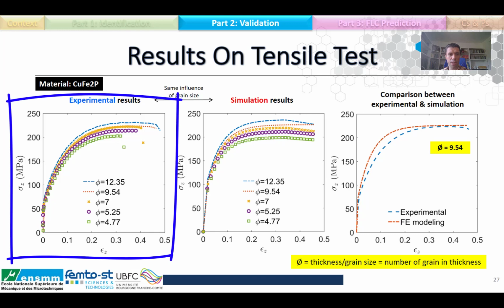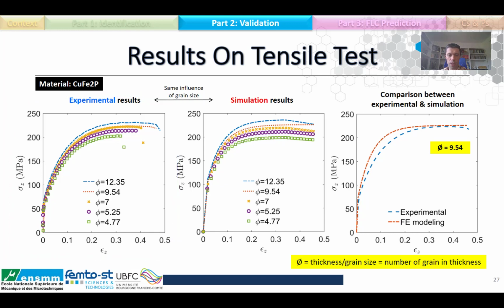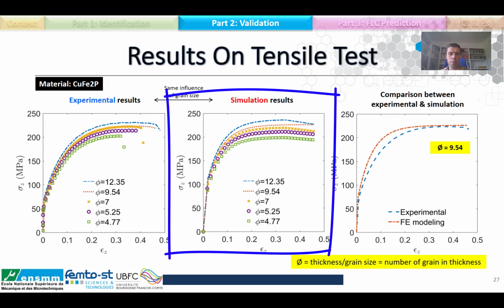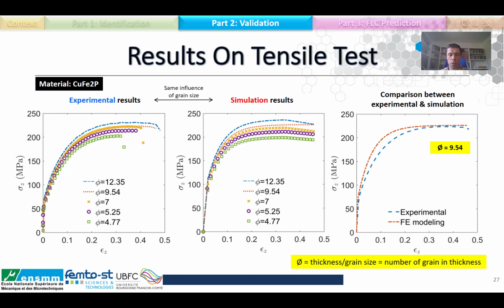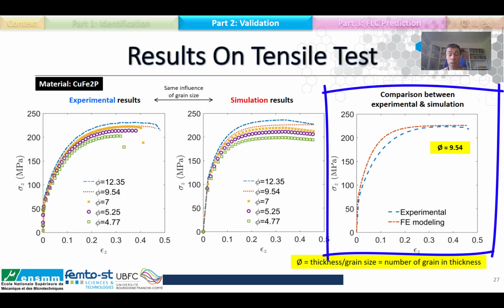The experimental results show a dependence of the mechanical behavior on the grain size. The finite element simulations are realized by using the material parameters obtained from micro-indent tests for each grain size. The simulation results show the same influence of grain size as the experimental results. By visual comparison to the experimental graph, the result obtained from simulation is coherent. For example, here for phi 9.54, the difference between both graphs is less than 5%.